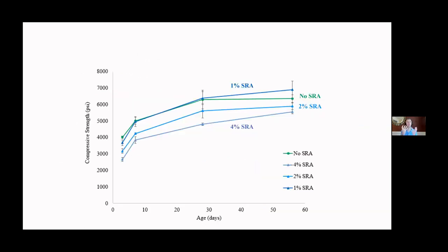Let's look at strength, the actual compressive strength of this concrete. Again, here's strength over here. Here are days, and this green line here is no shrinkage-reducing admixture. Here is 1%. Here is 2% and 4%, and that's 1% by weight of cement. And as you can see here, this 1% has almost the same performance. 1% SRA doesn't lose strength, but look at this.